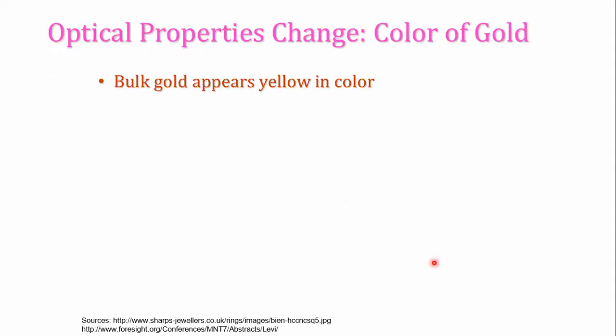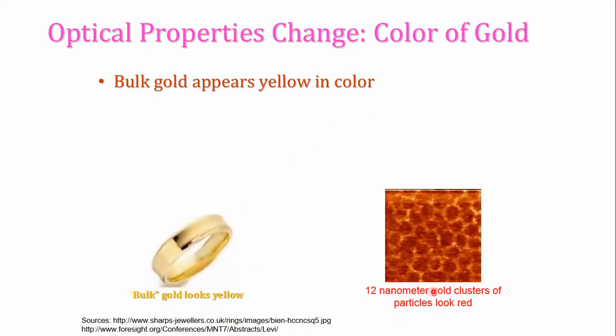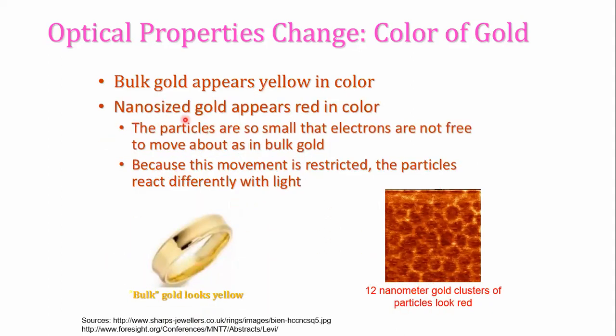Now if you come to bulk gold, it appears yellow, but at 12 nanometer size, it looks red. This is the same gold particle. So nano size gold appears red in color. At the 12 nanometer size, the particles are so small that electrons are not free to move about as in bulk gold. Because this movement is restricted, the particles react differently with light, that is, what they reflect or absorb changes with the size. That's why they look a different color, whereas in the bulk state, it looks yellow.